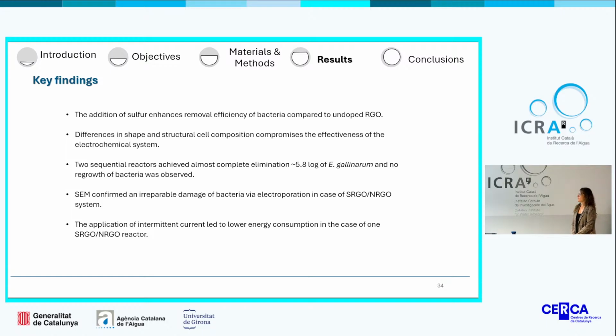So the main conclusions of this study are presented here. We could say that the addition of sulfur again enhanced the removal efficiency of gram-positive bacteria compared with undoped reduced graphene oxide. Differences not only in shape but also in the structural cell composition compromise the effectiveness of the treatment. Two sequential reactors lead to an almost complete elimination of gram-positive bacteria, in which no regrowth was observed. Also, the irreparable damage was confirmed by scanning electron microscopy, and the application of intermittent current led to a lower energy consumption in case of a single reactor.